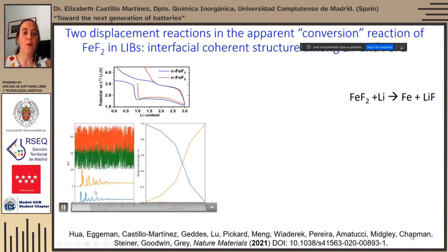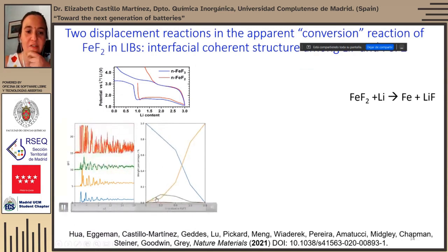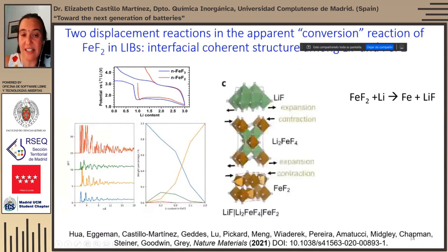Yeah. Well, that shows that by using a non-negative matrix factorization algorithm, a new phase appears, and this phase can be modeled very well as a lithium-2 iron tetrafluoride. And actually, this phase is thought to be an interfacial structure which is formed to accommodate the very large structural rearrangement between the iron difluoride and the lithium fluoride. But this phase can be coherently linked to both initial and final phases and seems to buffer the large lattice expansion and contractions between phases.